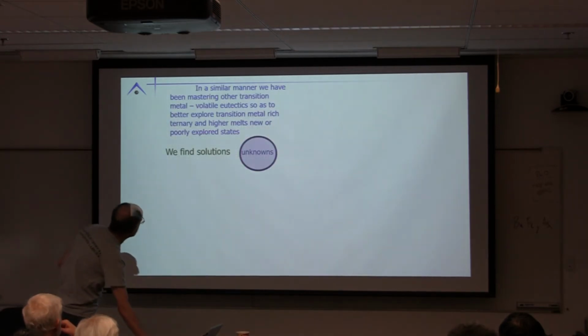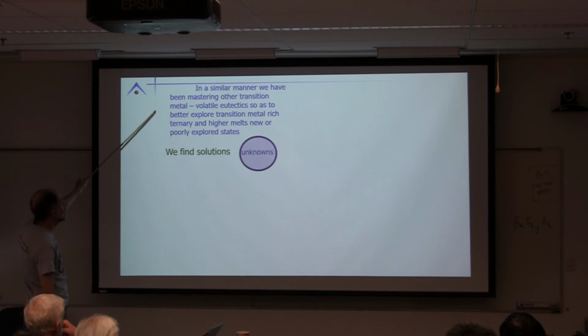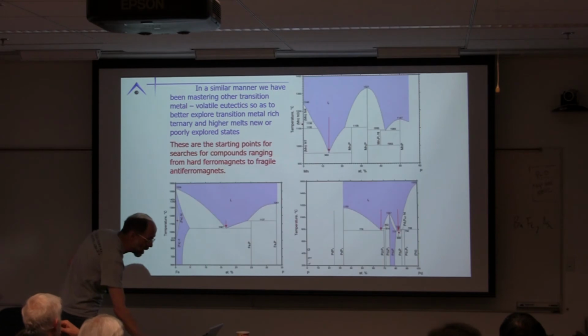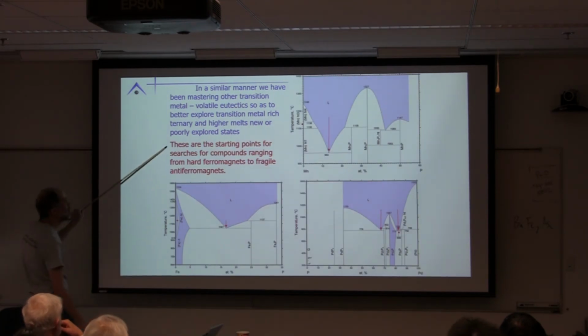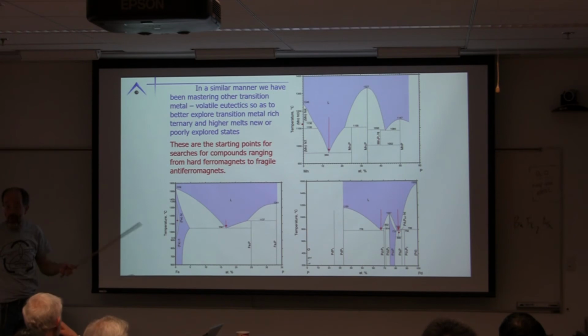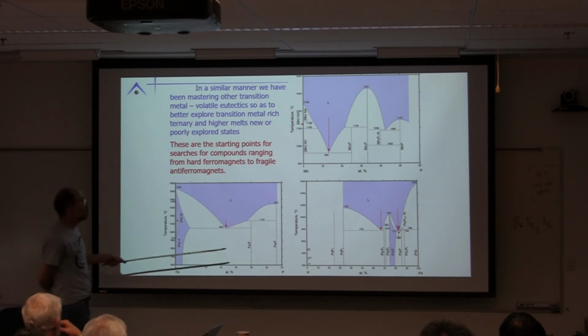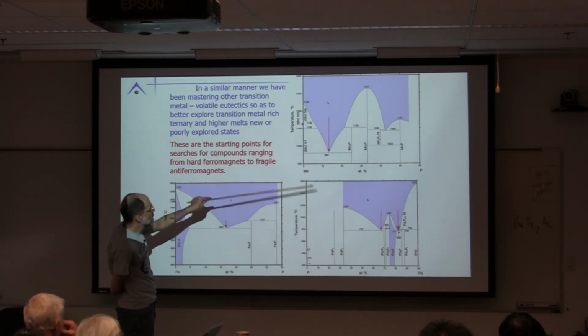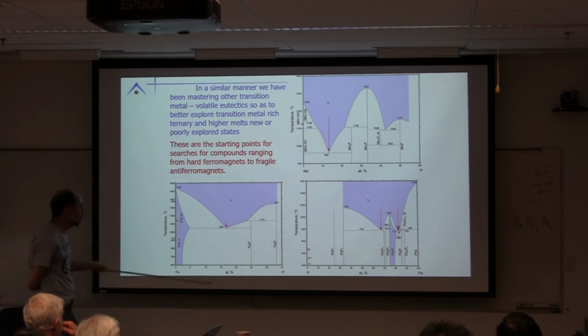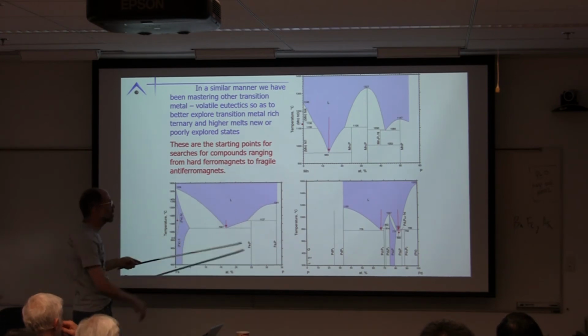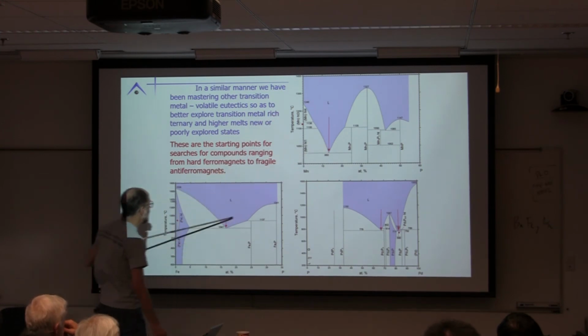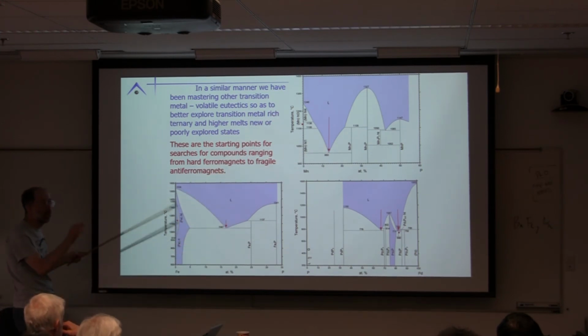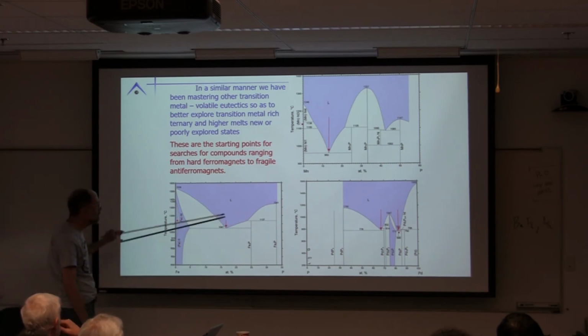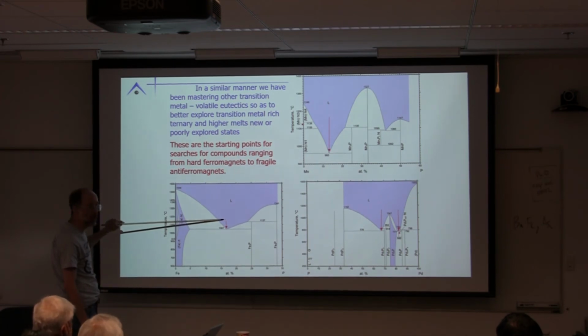But you can take that further. Okay? There are a lot of metal volatile eutectics that are interesting to explore. Okay? And since one of my other manifestations is trying to find new ferromagnets, even hard ferromagnets, okay? one of the places we've been looking is, for example, with phosphorus, you can look at manganese phosphorus, iron phosphorus, palladium phosphorus, cobalt phosphorus. There are often these beautiful eutectics on the transition metal side. We have walked into these very carefully, figured out how to react and how to get them into solution, and these are solutions that do not have too much vapor pressure over them.